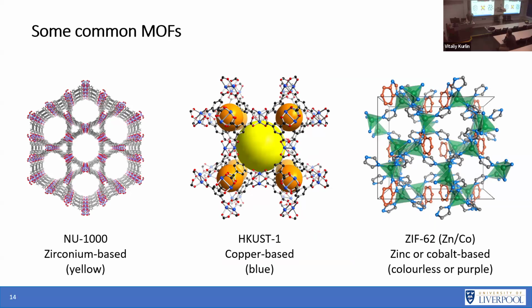The first one, this yellow one, is called NU-1000, and this is a zirconium-based MOF. The color actually comes from the linker in this framework. It's also an absolute nightmare to work with because it stains everything in sight yellow. We've got the blue one, which is HKUST-1. Any guesses for the metal here? It's copper-based.